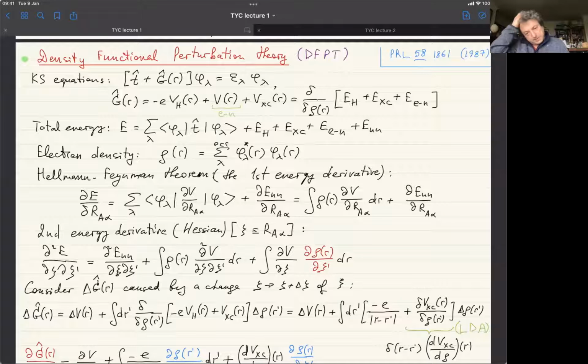The problem with that method is that in order to get access to K points which are close to the gamma point, you need very large cells. Because as I tried to explain last time, only K points which fall into the gamma point of the reduced Brillouin zone, due to the extension of the primitive cell into that extended cell which is actually used for the calculations, will be reproduced. So if you have a K point near the gamma point, you have to have a very large extended cell so that that point would become the gamma point of the reduced cell.